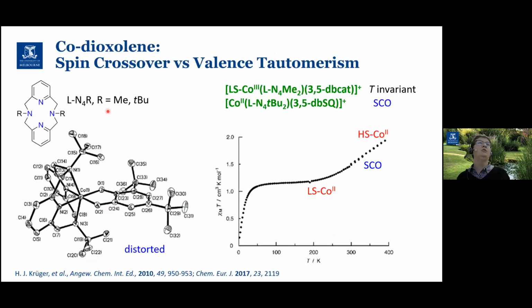Okay, so one other literature complex I want to talk about is actually related. So a cobalt complex, again, 3,5-ditertbutyl dioxolene, and now a pyridinophane azamacrocyclic ligand. It's a 12-membered azamacrocycle. This is from Hans-Jörg Krüger's group in Kaiserslautern, published and communicated initially in 2010. So they demonstrated, again, really interesting control of the switching again by the ancillary ligand. So they reported 2 analogues in this initial communication.